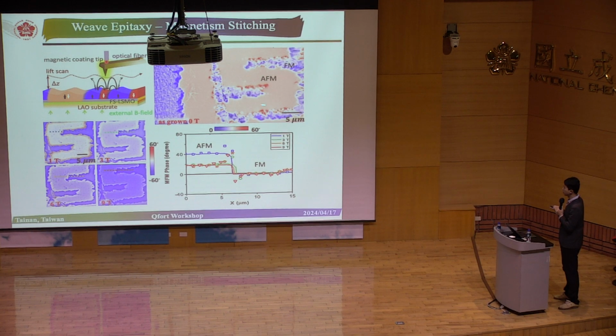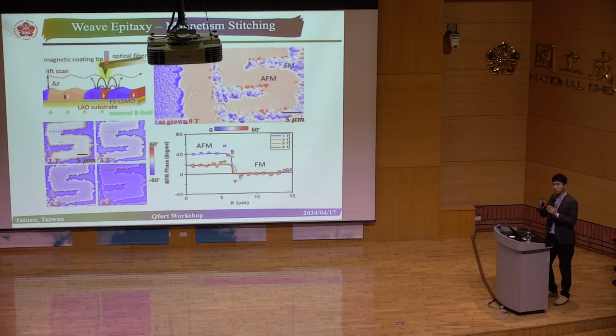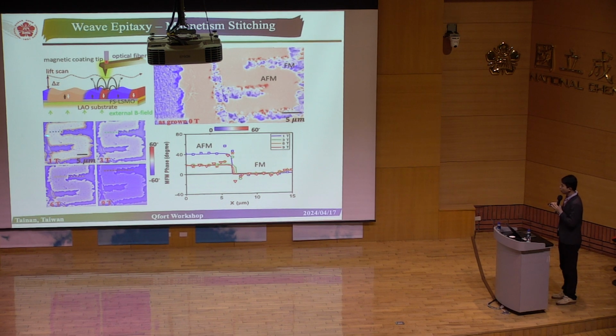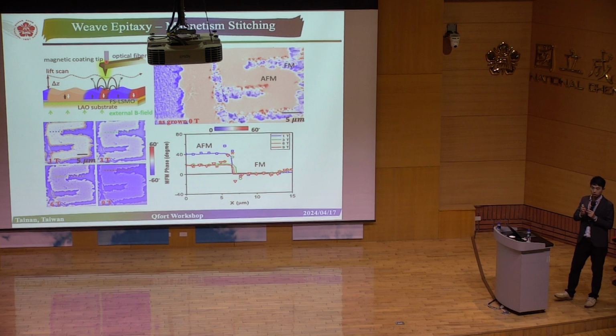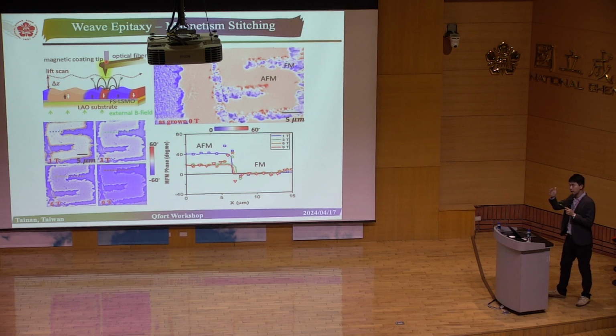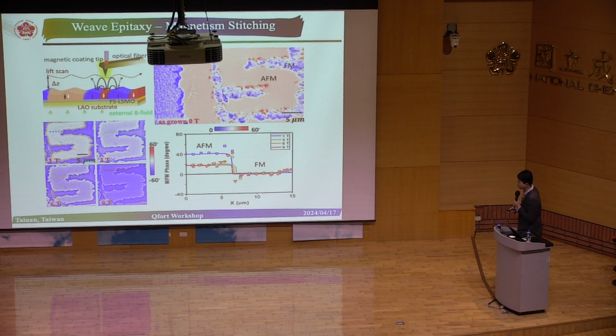In the inner area, basically there's no response for the magnetization. So this is the antiferromagnetic region. If you look at the outside area, it's composed of a ferromagnetic matrix. They are basically unstrained LSMO. If you try to enlarge the magnetic field, for example, you start from 1 Tesla, 3 Tesla, 6 Tesla to 9 Tesla, what we essentially see is that the dark or the bright contrast starts to become blue. It also suggests that through the application of the magnetic field, you will assist the antiferromagnetic phases to become ferromagnetic ones.